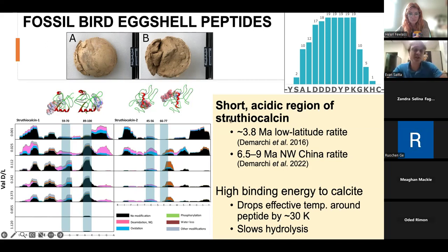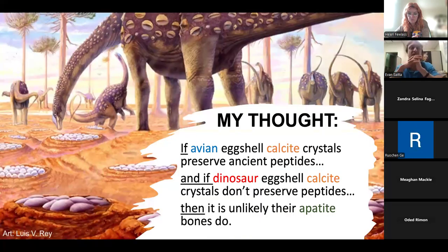And so struthiocalcin, for example, is a protein that's involved in mineralization of the eggshell, and a particular region of it, a very short and acidic region, has been detected in higher latitudes, perhaps as far back as 9 million years old. But even at low latitudes, 3.8 million years old, which is quite surprising given the temperature regimes down there. And the hypothesis being that there's a high binding affinity for this particular region to the calcite based on the function of the protein, and that this binding stabilizes the protein, which can be thought of as essentially dropping the effective temperature around that sequence by about 30 degrees Kelvin, which would then slow hydrolysis. So it's sort of like a molecular equivalent to freezing this protein, and allows for the sequence to survive far longer than it might otherwise.